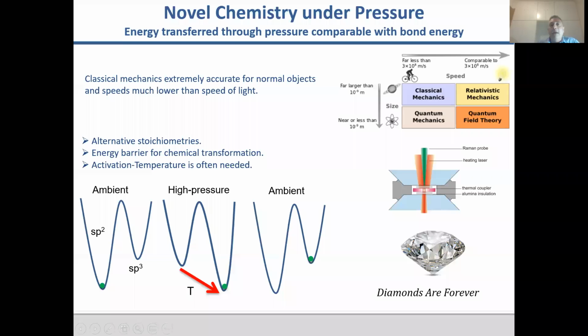Usually, and I think this is well known in the field, one of the main problems is that we need to overcome energy barriers for chemical transformation. Here I just show a very simple example of diamond and graphite. At ambient conditions, you have sp2 as the stable configuration. You go to high pressure, and you need some temperature to overcome the barrier. And then the trick, what we are trying to do here, is to have materials that are quenched, which means metastable at ambient conditions. When you release the pressure, the energy landscape returns to the stable one at ambient, but due to the inverse barrier, the system may be trapped. And this is more or less why diamonds are forever.